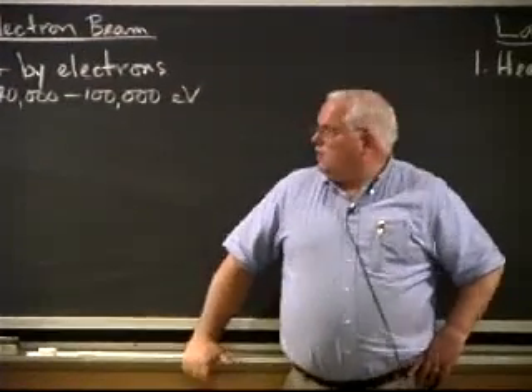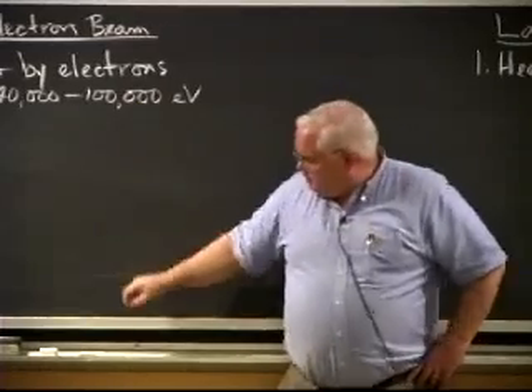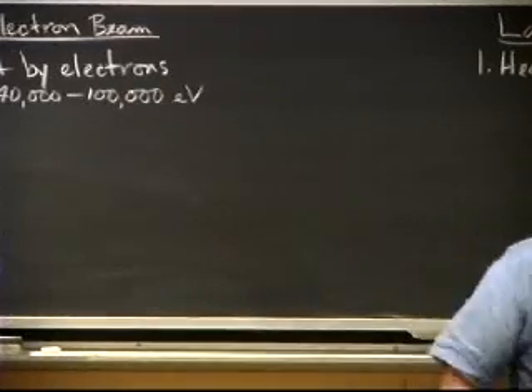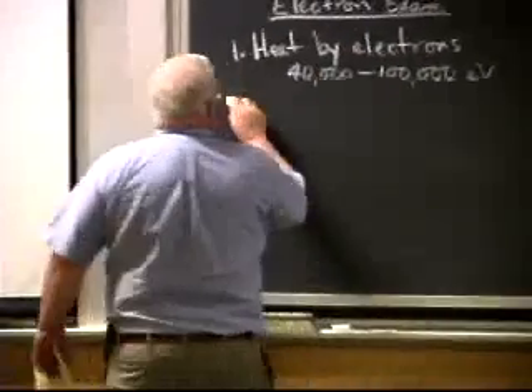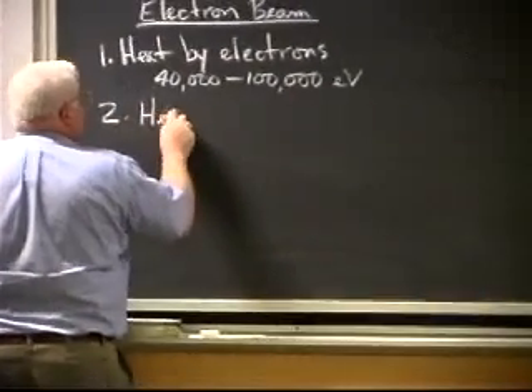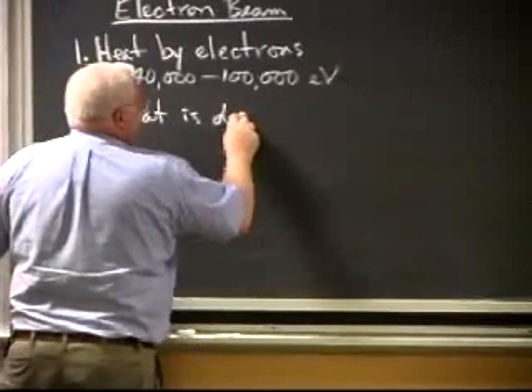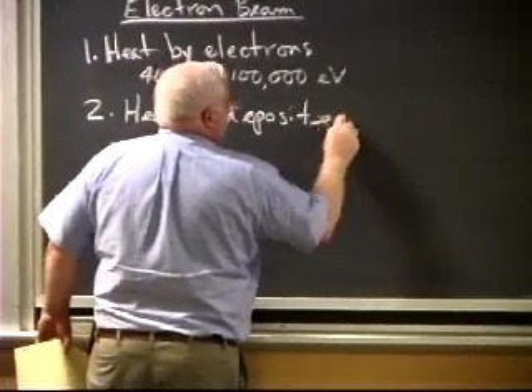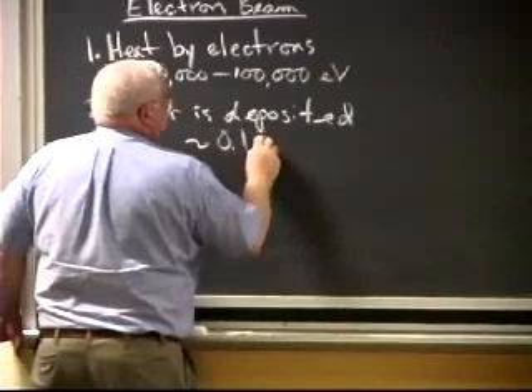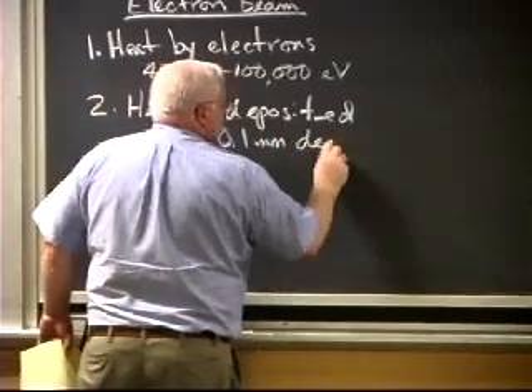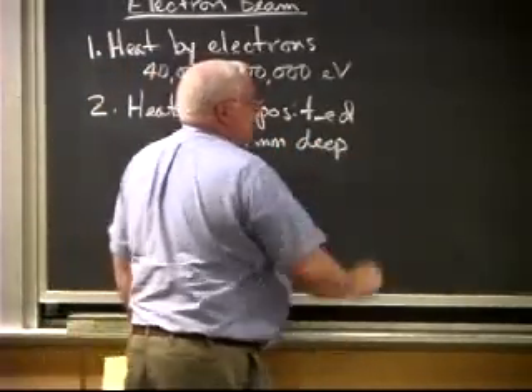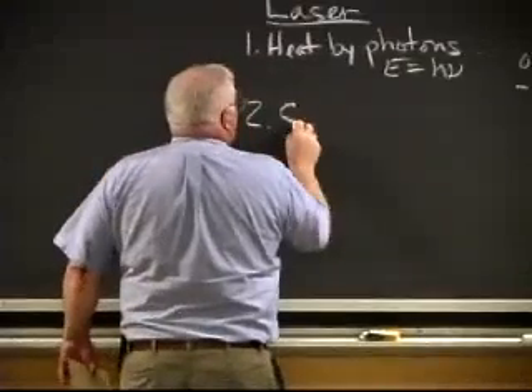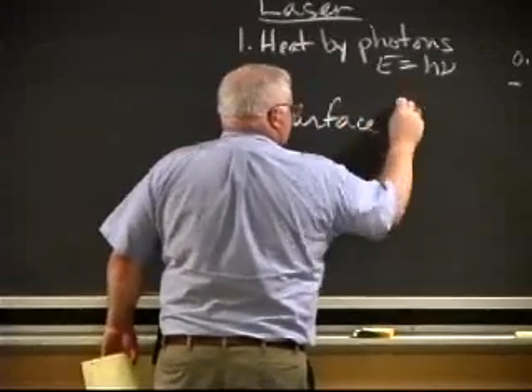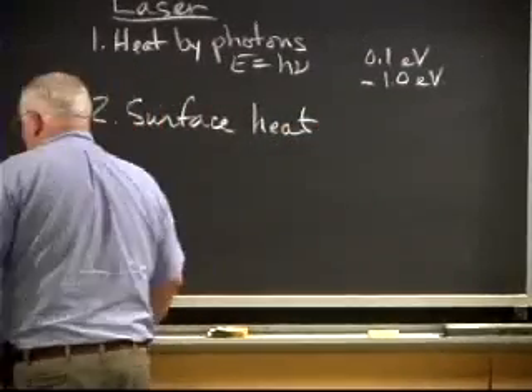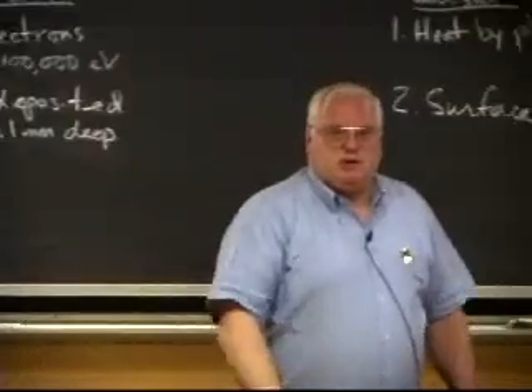And why is that important? Well, it turns out this does subsurface heating, which I think is my second point. Because of the energy difference, heat is deposited about 1/10 of a millimeter deep. That's about a human hair, right? It's not very deep. And this is all surface heat. And you say, well, does that make a difference? It turns out it does in some cases.